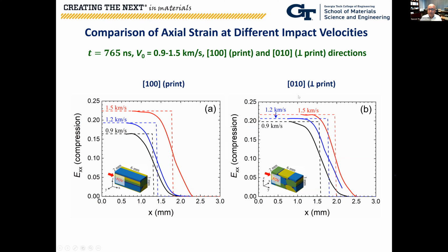If you look at the 0-1-0 condition, notice that the overall peak is still within that range, except there is lesser deviation in the strain—literally between 20 to 22%—whereas in the 1-0-0 orientation, the maximum strain as a function of impact velocity ranges from about 16% to about 24%, or 20%. So there is some local strain effect being manifested by the orientation of the print, but otherwise the equation of state response, the bulk shock compression response, seems to be independent of the print orientation.